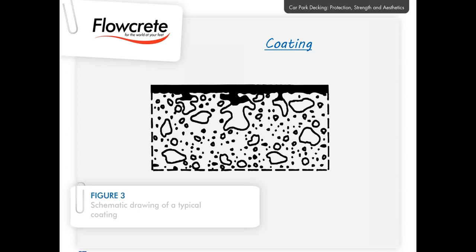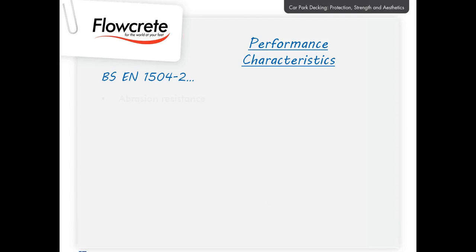This is accomplished by protecting the reinforcement bars from chlorides or by changing the moisture content inside. When the concrete is treated with a water repellent agent, the properties of the surface layer becomes hydrophobic, and therefore water droplets are stopped from entering, but they still allow water vapor to pass through the slab. This change can reduce chloride ingress and stop heavy rain from penetrating through the surface layer.